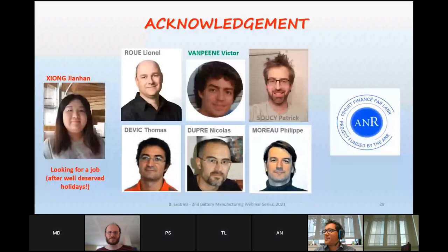New question: thank you for the great talk. Could the benefits of the maturation process be achieved by artificially adding water to the slurry to shorten the electrode preparation times? Or are there other processes involved in the exposure to moist air that result in the improved electrode properties? In fact, the electrode slurries are prepared with water. So we have water, but it seems that we need this slow corrosion process to allow for copper diffusion. But it seems that we could obtain the same performance improvement by simply adding copper or other coordinating cations inside the electrode slurry.